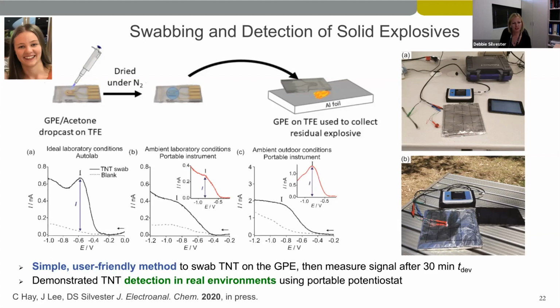And what you can see here is the square wave voltammetry responses. Under ideal conditions, in figure A, you can see a nice sharp peak. And then as we go to our ambient conditions, because we've got more moisture and background contaminants, we still see a peak, but it's more broad. And when we do a background subtraction, you can see the red line then shows the response for TNT. This method is very simple and user-friendly, and you can measure TNT within 30 minutes or less, and it's a good way to identify if TNT is present, and then you can detect this in real environments.